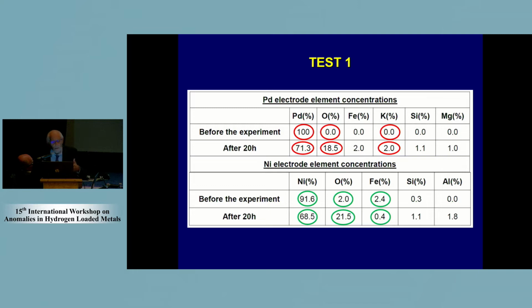Even if we have many elements that were analyzed before and after the test, you see the palladium usually decreases between 25 and 30% in the 4 tests, very repeatable. We have the oxygen, which increases between 15 and 20%, and then we have other smaller variations. And I underline the fact that potassium is appearing, plus 2% in this case, experimentally. Theoretically, we will see that there is a small deviation.